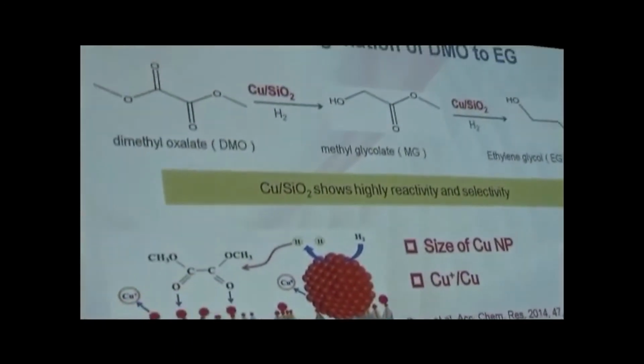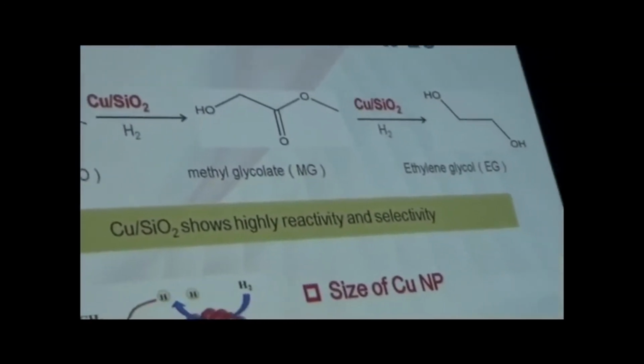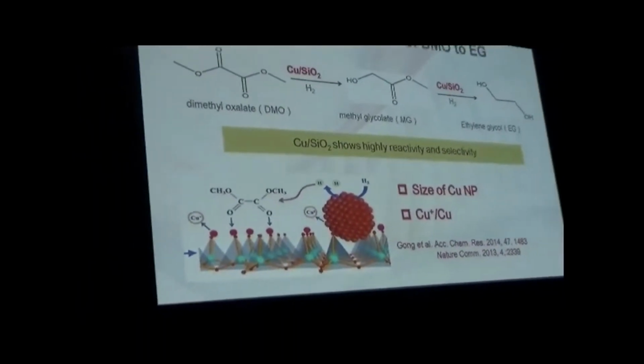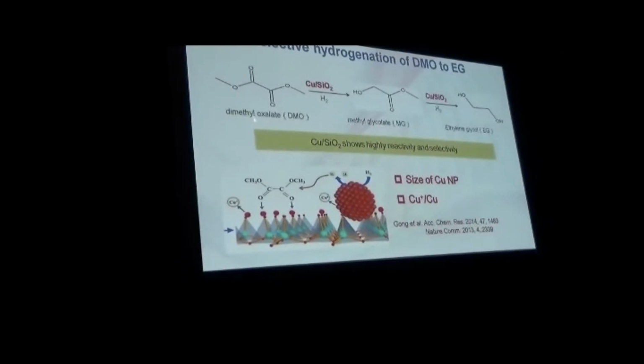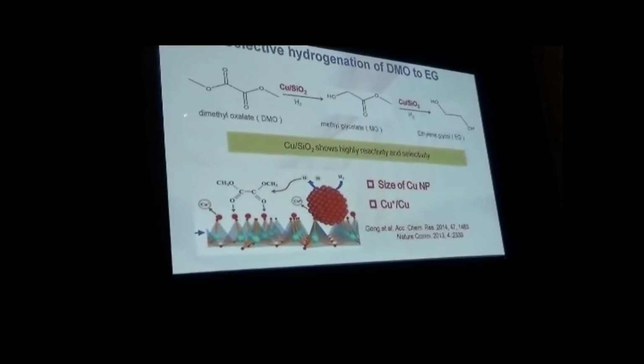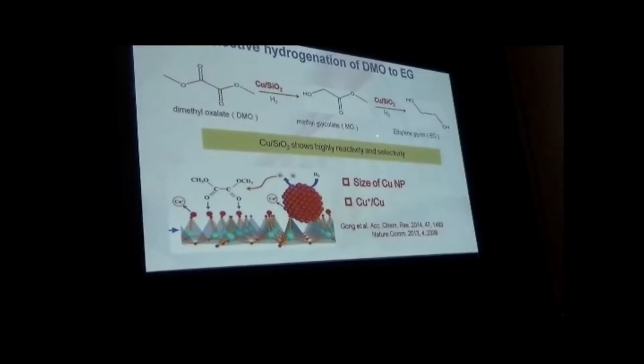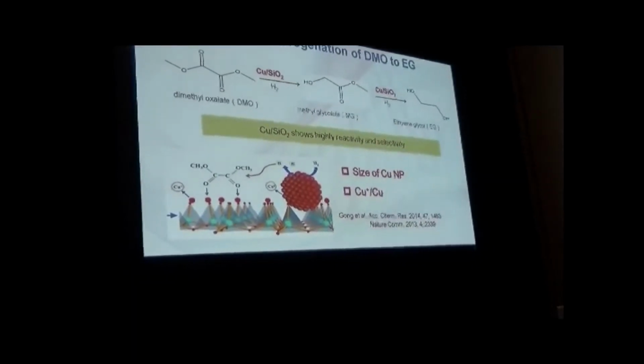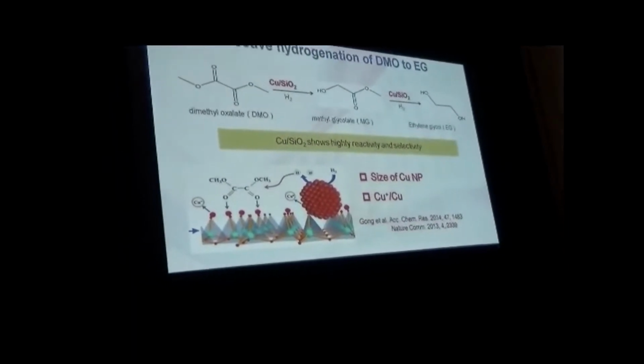Because the support, when we use support effect, we also see the support effect on the reducible oxides, like iron oxide and titanium oxide. How about the irreducible oxide? For example, silicon oxide. The copper silicon catalyst is very good for the hydrogenation of dimethyl oxalate. This is the final step from coal to ethylene glycol. It's a very important industrial process now in China. This is the final step.